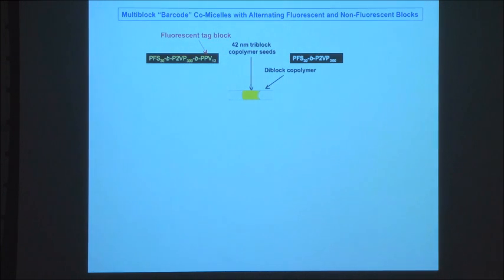Here's an example where we start with seeds here, which are based on PFS poly-2-vinyl pyridine, with a little bit of a fluorescent tag at the end. So this is polyphenylene vinylene, just on the end of the coronal chain to give you a fluorescent tag. So that's the yellow seed we start with. We then add to that the block copolymer without the tag, so that adds each side. And then you add this one again, so it adds to the ends of that. And then you can build up structures like this, barcode type structures. And when you do this, there's always a plane of symmetry in the middle here because the seeds will grow from each side. So you always have a plane of symmetry with these structures.